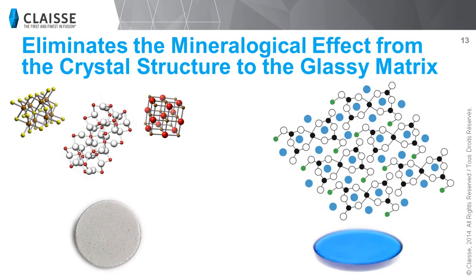Sample preparation by fusion is the perfect method to eliminate these mineralogical and particle size effects. The pressed pellet contains different crystal structures. However, as illustrated here, glass discs are ideal for XRF analysis since they are vitreous and the components to be analyzed are homogeneously distributed in the glassy matrix.